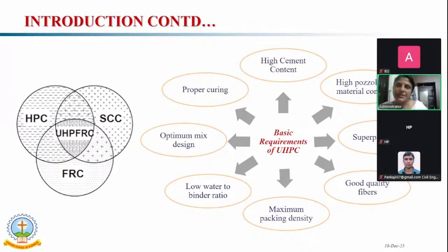The curing practices are taken from the literature and from our experience. Actually, there are three types of curing practices we can adopt. The normal curing, that is the water curing. Mainly in the case of UHPC, we have considered heat curing. Heat curing has different types, the hot water method and the steam curing. We have followed the steam curing.